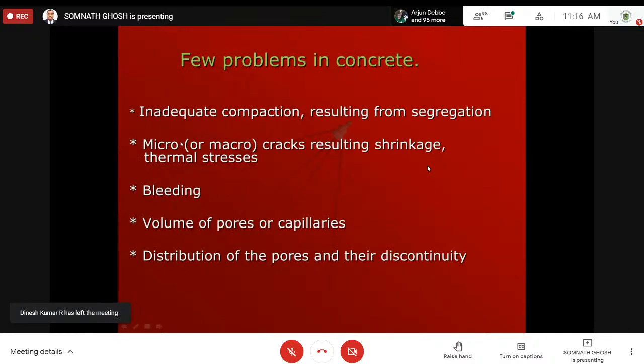Now you see a few other problems: inadequate compaction resulting in segregation. You all know. Microcracks resulting from shrinkage and thermal stresses. So you have to be very careful of shrinkage and thermal stresses. If you don't take care of those things, then there will be huge shrinkage cracks initially. Then bleeding is another problem. If you keep the concrete in a particular place, you will slowly find that even if you do nothing, water is coming out from the concrete. Concrete should be able to hold the water you have given. If it is coming out, it will become harsh. Then the volume of pores and capillaries is to be controlled. Then the distribution of pores and the discontinuity. If there are pores and the pores are interconnected, that is bad.